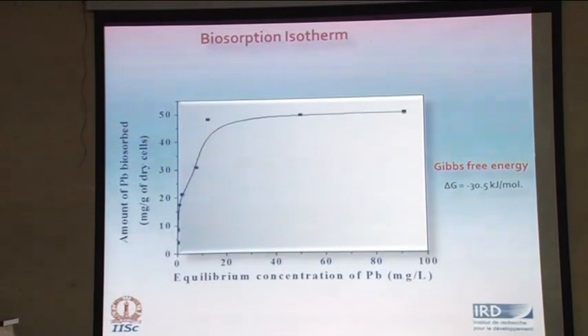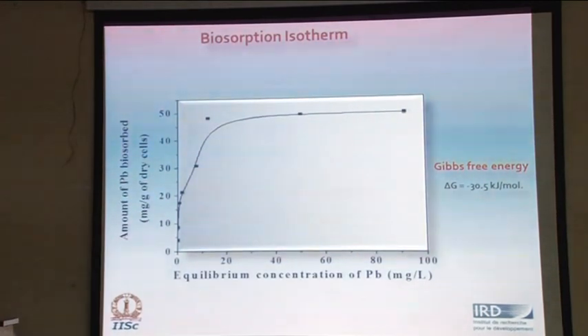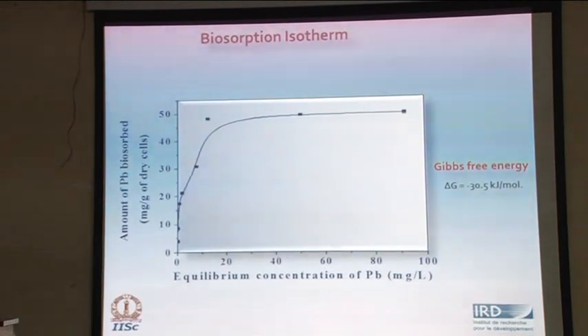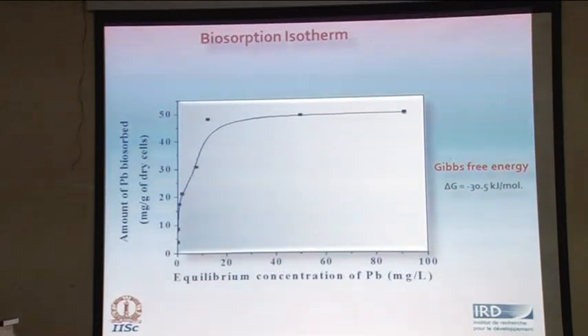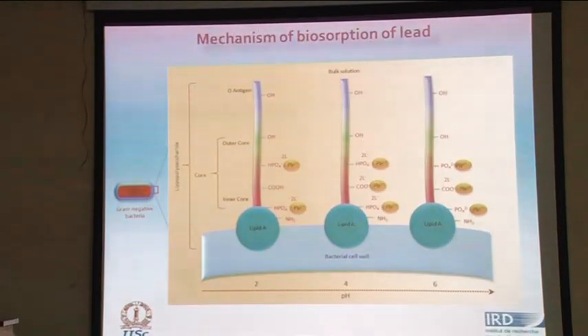What is important also is to look at the biosorption isotherm. So you can see that it follows the typical Langmuirian behavior. The free energy is of the order of minus 30 kilojoules per mole. Again, the reaction is quite favorable. And then you can use this data for building up the parameters for the scale-up.